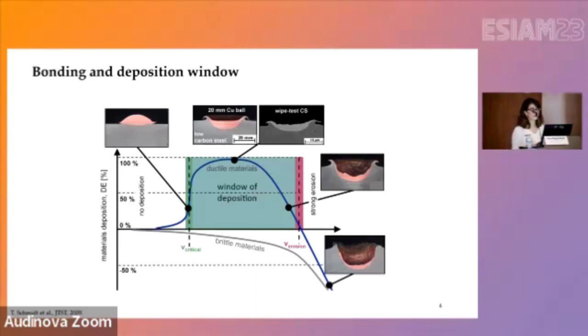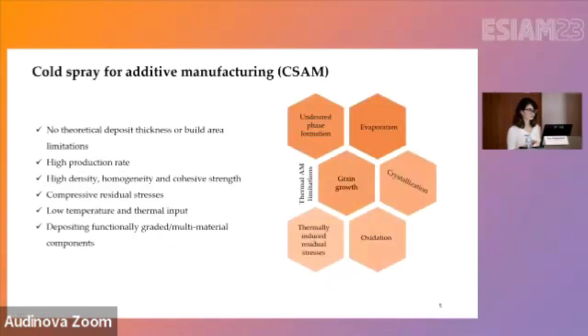And as we increase the velocity further, we get to the range of eroding the substrate and removing material. So it's very important to identify the window of deposition for the material that we are trying to spray based on its thermomechanical properties and the properties of the substrate material.